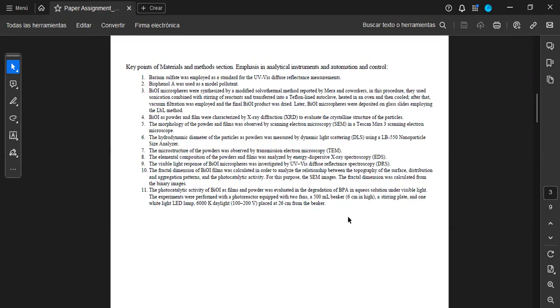under visible light. So these experiments were performed with a photoreactor, and this was equipped with two fans, a 500 milliliter beaker, which was 6 centimeters in height, a stirring plate, and one white light LED lamp. And it was in the mode of 6000 K daylight, which is 100 to 200 volts, and this was placed 26 centimeters from the beaker. So this is the first part of the analysis of this paper, which studies the photocatalytic activity of these films.